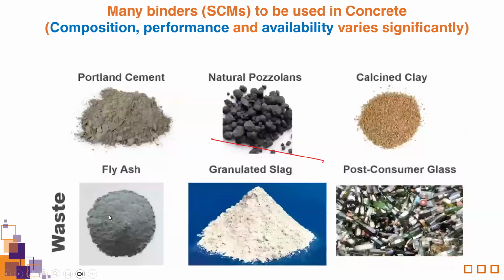Then the most popular one is the fly ash, which is the byproduct of coal thermal plants. We have granulated slag, blast furnace slag. This is the byproduct of the steel industry. And there is glass. If we grind the glass, make it powder, we can also use it as a supplementary cementitious material. And there are so many other materials, the agricultural waste, and so many other industrial waste. It can be used as a binder, especially as a cement replacement in the concrete. So the problem is that clinker is producing a lot of emissions. If we replace clinker by some percentage with those materials which have low embodied carbon, then we are reducing the emissions of the concrete.